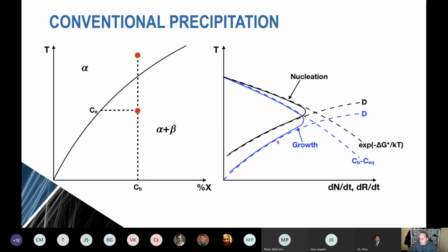This is all well known, and we've been doing this for 80 or 90 years now. But it's useful to remember what underlies this C-curve behavior. This is a competition between thermodynamics and kinetics, and it leads to us choosing an intermediate temperature for our heat treatments of precipitate hardened aluminium alloys. We do that so that we can make a reasonably fine distribution of particles, but we don't have to wait forever for that to happen.